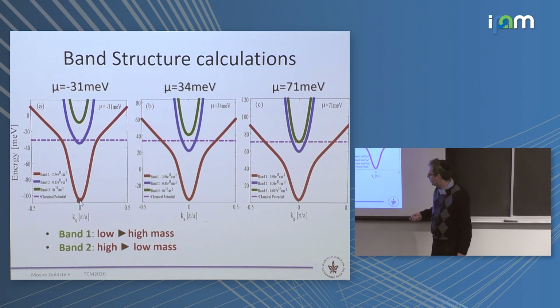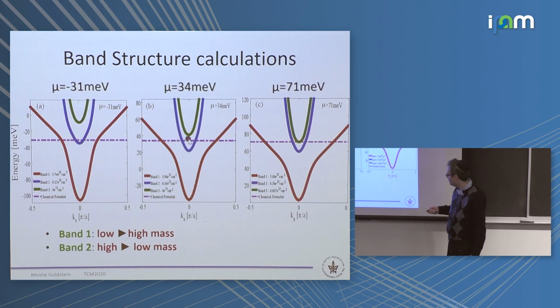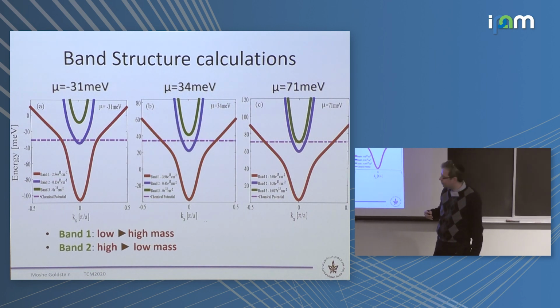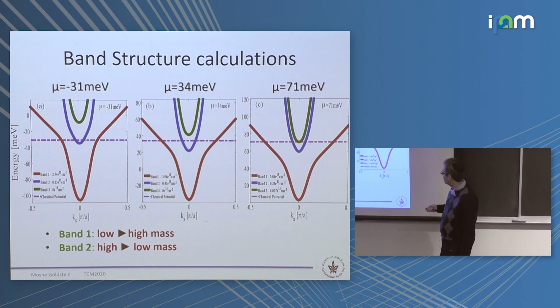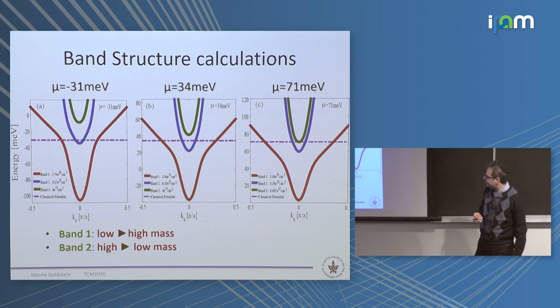What you find is, first of all, this is a general thing. The first band starts with low mass, then it becomes high mass because they mix. And the second band starts high mass and then becomes low mass. As you start filling in and increasing the Fermi energy, you first fill this one, then you start filling the second one, and here it has high mass, so you actually like to fill it, and you keep filling it. As you increase the Fermi energy, this becomes low mass, and then because of the competition, you actually regret filling it. You take the electrons out of it and put them in band number 1, which has a higher mass. So this is a more complicated version of the simple story I was showing you with cartoons before.